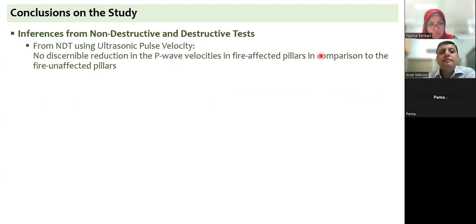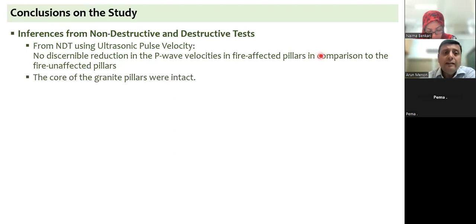Now, from the non-destructive tests, we did not see any reduction in the sonic waves in the fire-affected pillars. We expected it to have some changes in the sonic wave velocities, but this was not happening. And that was really because of the small sizes of pores that we're talking of in granite, and sonic velocity not being able to discern the difference between pores that are affected and pores that are not affected. But it was very clear that this was coming across because the core of the granite pillars were intact. It was really the exterior layers that were badly affected by the fire. And given the low porosity, the exterior layers were getting damaged by flaking. But the core of the granite pillars, in most cases, were intact.